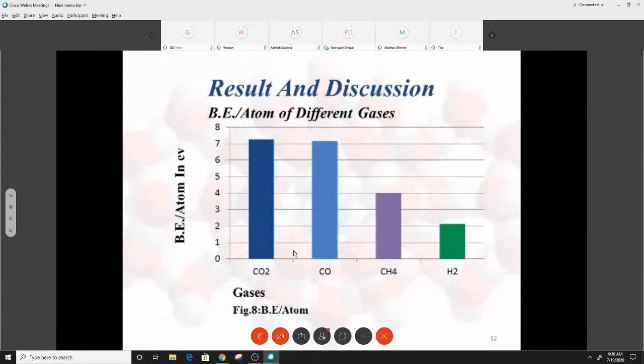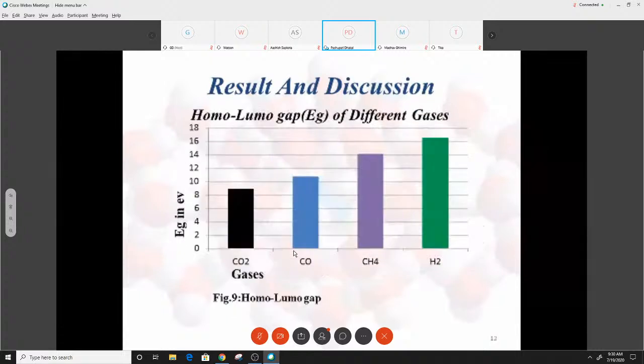So the higher binding energy per atom of CO2 and CO, and the lower binding energy per atom of methane and hydrogen shows that methane and hydrogen are less stable than the CO2 and CO. Similarly, here we can see that the HOMO-LUMO gap of methane and hydrogen gas is greater than the gap of carbon dioxide and carbon monoxide. So it also shows that methane and hydrogen gas are less stable.